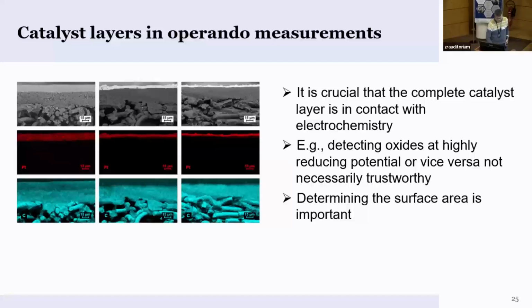depending on your ratio of platinum to carbon that you would like to study. And in electrochemical systems, this determination of the surface area is really important, because if you have a thick catalyst layer and, for example, come with a beam through the catalyst layer, and you don't have full electrochemical connection to your catalyst layer, then you might see, for example, oxides at potentials that are very reductive. So that's often reported. But the main question is, is that simply because you don't have electrochemical contact to it?